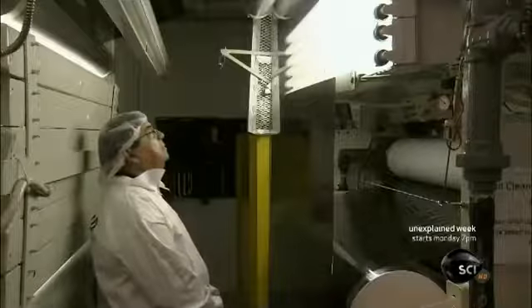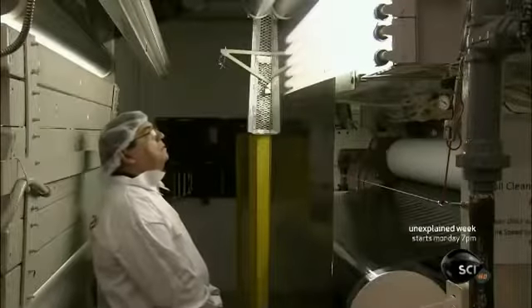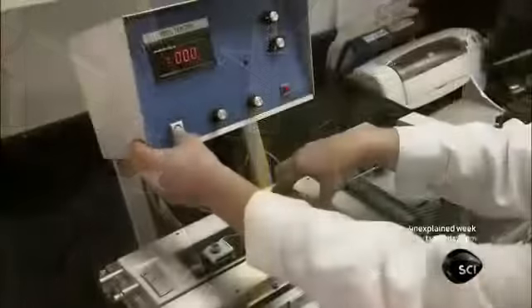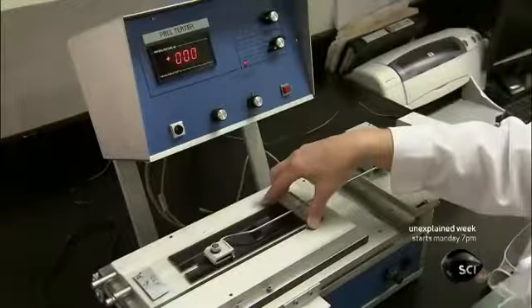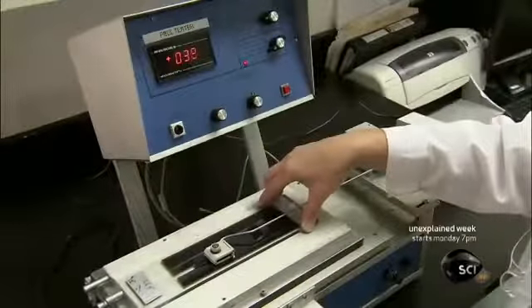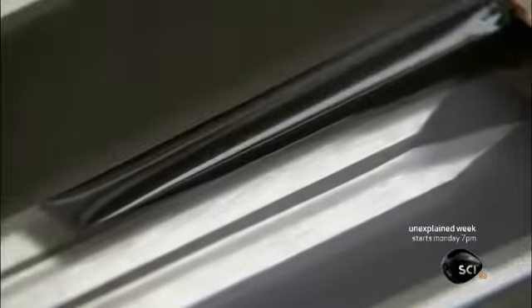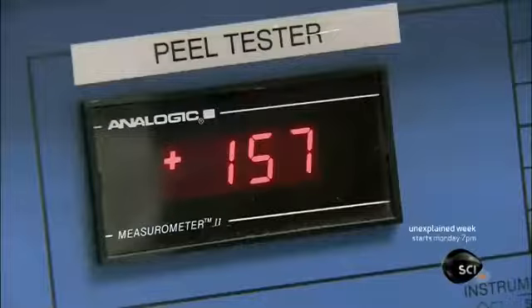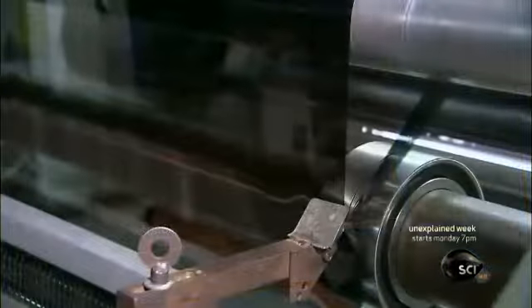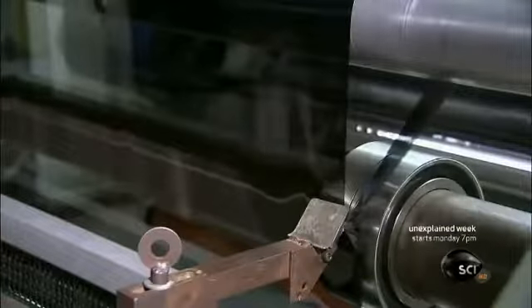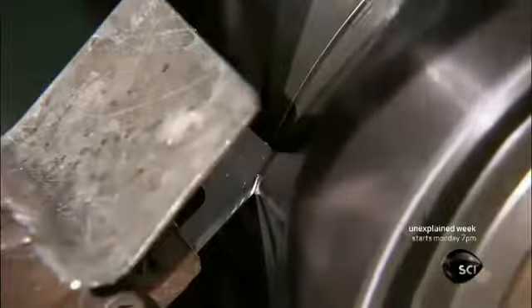A computerized system checks for defects, and a worker does a double check as the film passes in front of a bright light. After a third film, mounting adhesive and release liner have been applied to the product, a technician tests a sample. She pulls it off a piece of glass, and a sensor measures the amount of force it takes. The test confirms the window film grips the glass adequately. The production run gets the green light.